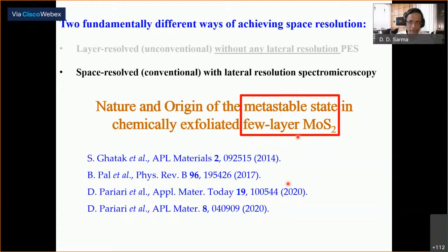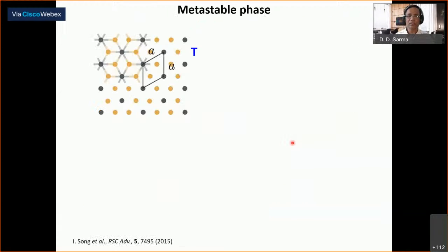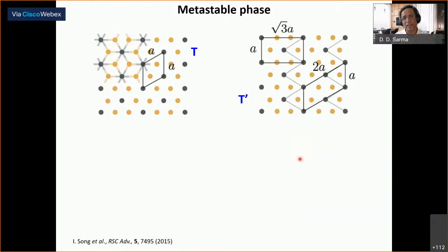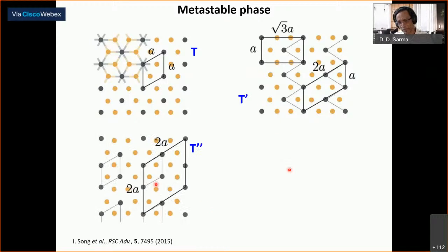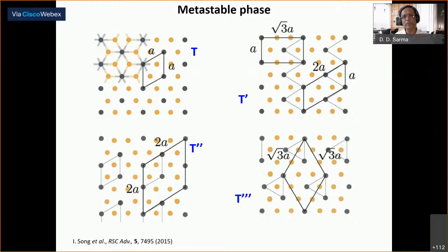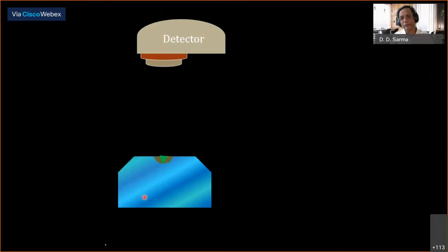is a conference on heterostructure, but quickly tell you that this metastable state can be in many different crystallographic forms, T, T prime, T double prime, T triple prime, etc. Using this technique, basically it forms in small patches. Imagine that you have an MoS2 which has some stable form, which is the H form, and some unstable form, T form, which is this little green part here, and the gray part is the stable form.